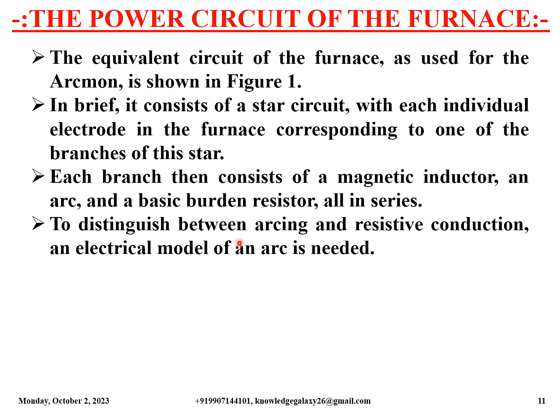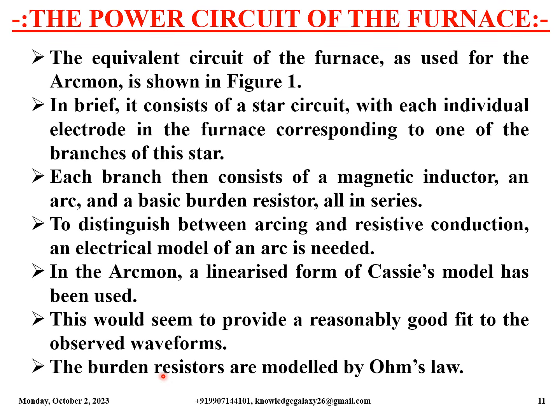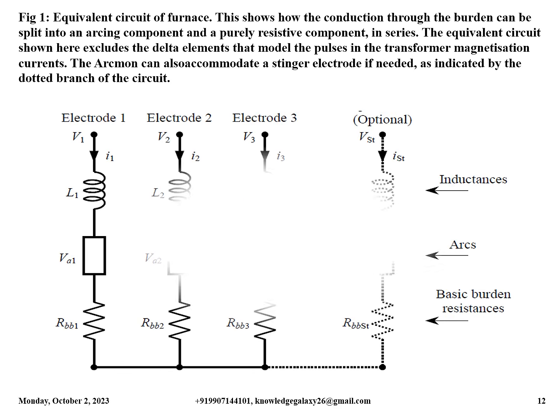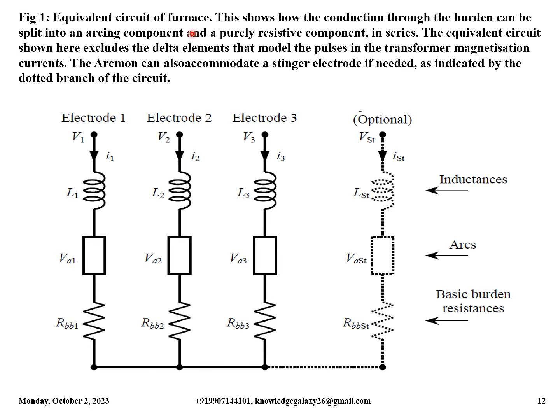To distinguish between arcing and resistive conduction, an electrical model of an arc is needed. In the ArcMon, a linearized form of Cassie's model has been used. This seems to provide a reasonably good fit to the observed waveforms. The burden resistors are modeled by Ohm's law. So this is the equivalent circuit of the furnace.